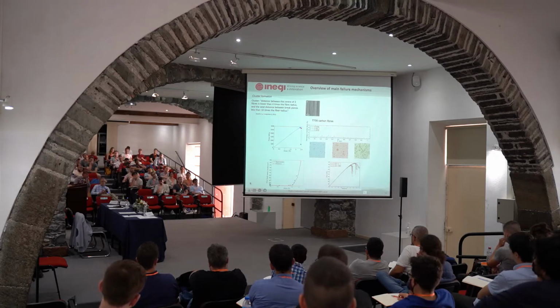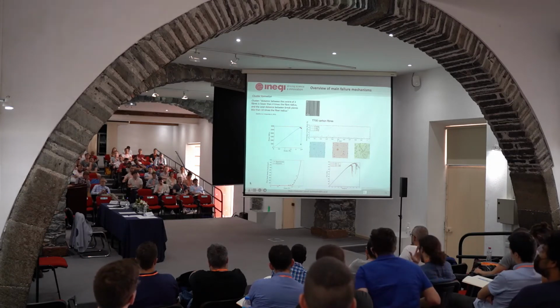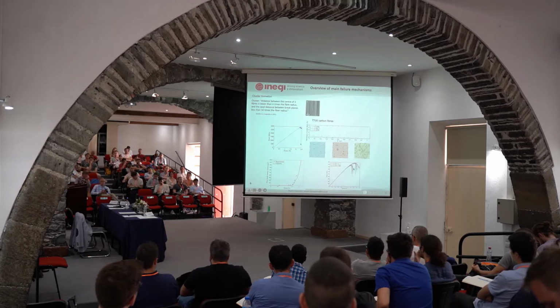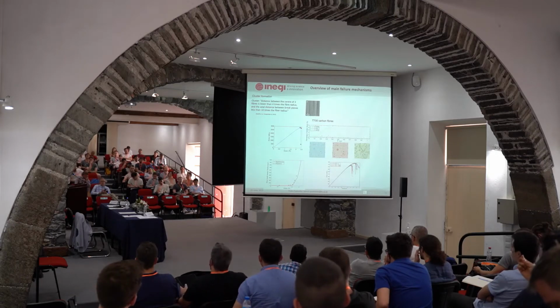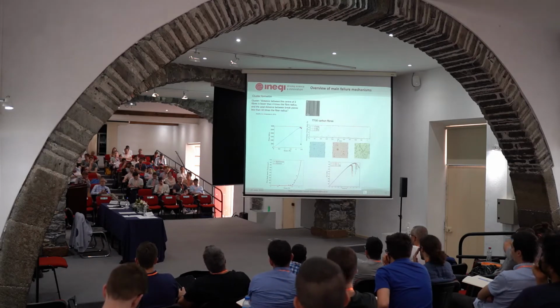Okay, so again, we use the data that was obtained at the synchrotron to further validate the model in terms of the fiber break density with respect to the ply strength, so experimental and numerical. And what you can see here is that we are playing around with the different properties. We are playing around with the properties of the resin. So that means that, for example, we can play around and design new materials without having to make and break the materials. So, for example, we had a project on hybridization of different types of fibers.